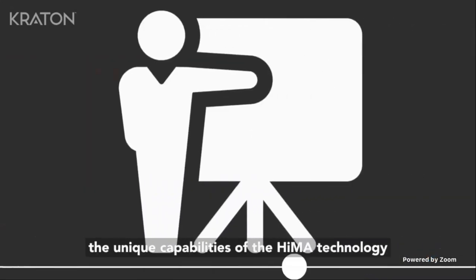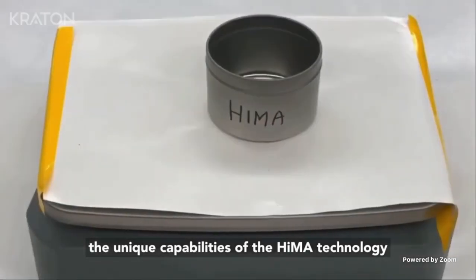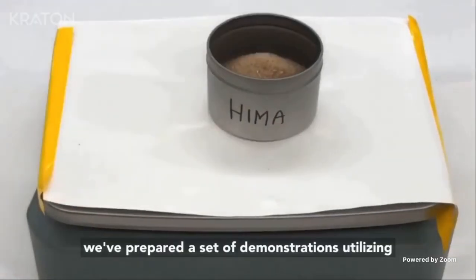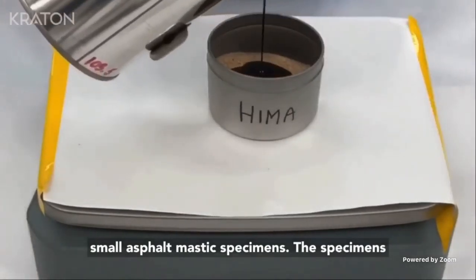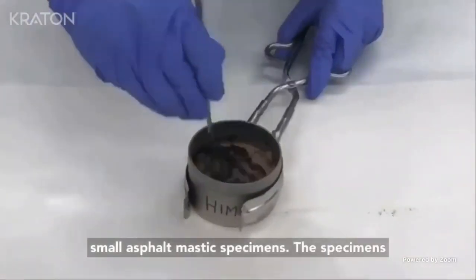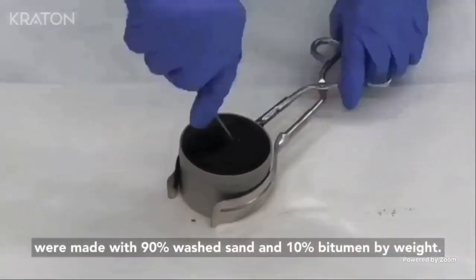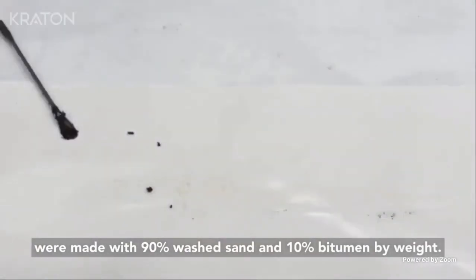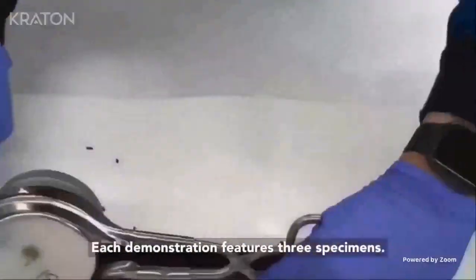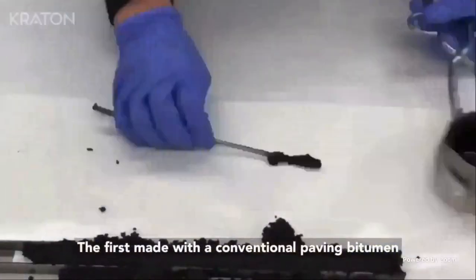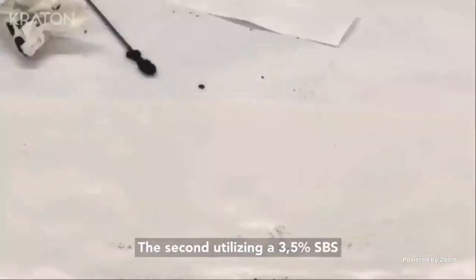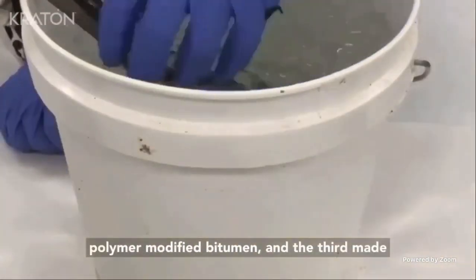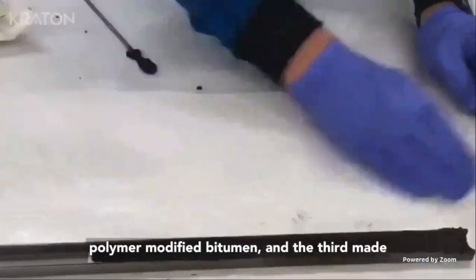To illustrate the unique capabilities of the HiMA technology, we've prepared a set of demonstrations utilizing small asphalt mastic specimens. The specimens were made with 90% washed sand and 10% bitumen by weight. Each demonstration features 3 specimens. The first made with a conventional paving bitumen, the second utilizing a 3.5% SBS polymer modified bitumen, and the third made with a highly modified bitumen.